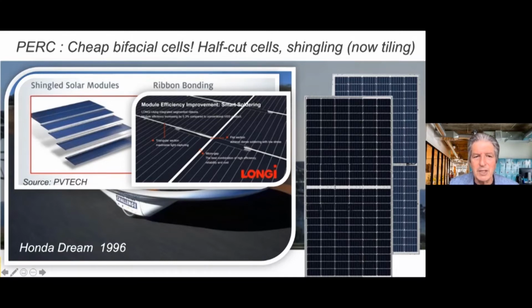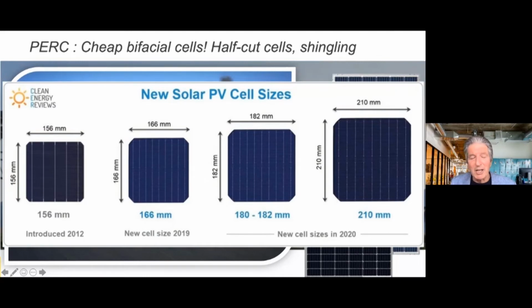So in this slide shown in the center there at the top, in the regions away from where the cells are interconnected, the ribbon interconnect that's soldered onto the cell metallization has a triangular cross section in the upper regions. That's to reflect light from the metal onto the cell so you don't waste it. And then in the region where the interconnection between the two cells occurs, it's flattened right down. So you have a very thin cross section, which helps with stress relief and everything with the interconnections between the two cells and allows them to be more closely spaced. So this is technology that's happened at the same time as PERC was introduced, and largely due to the fact that the PERC allows easy cutting of the cells into subcells.